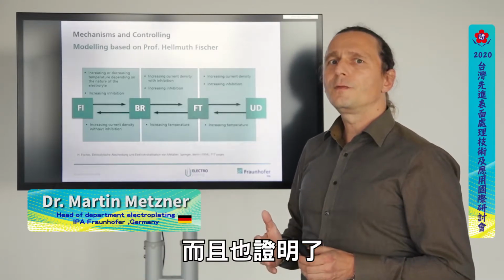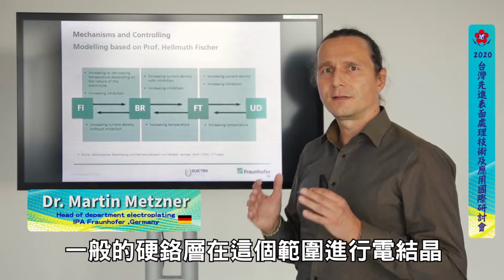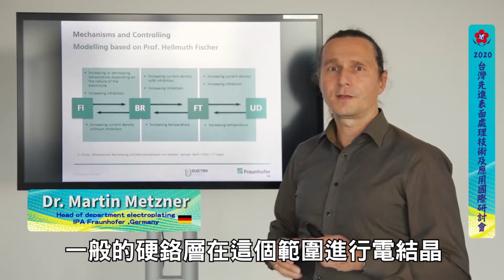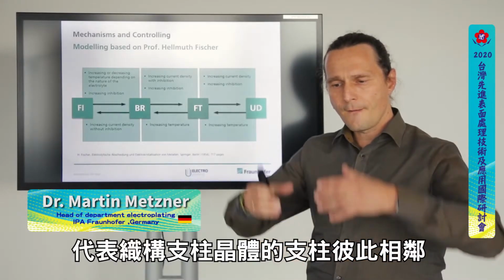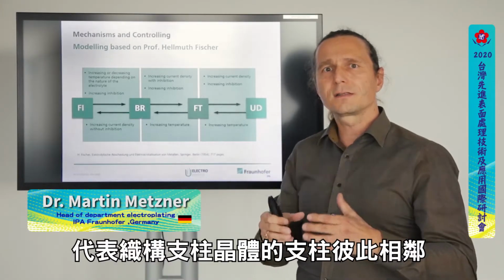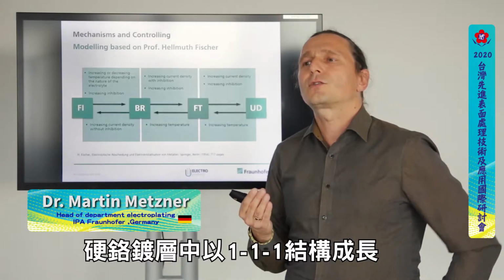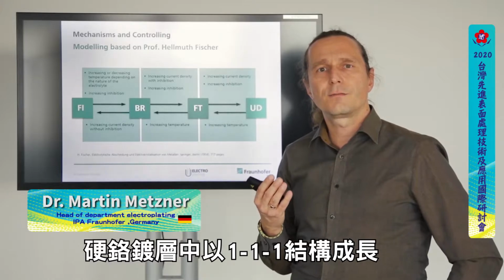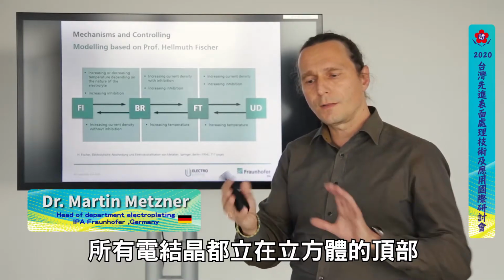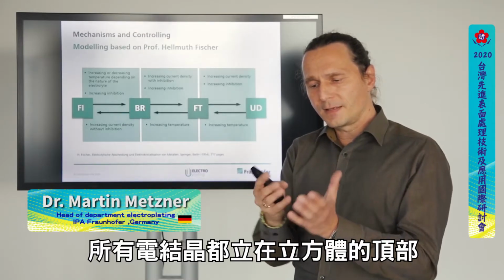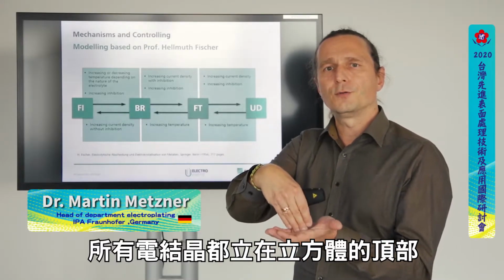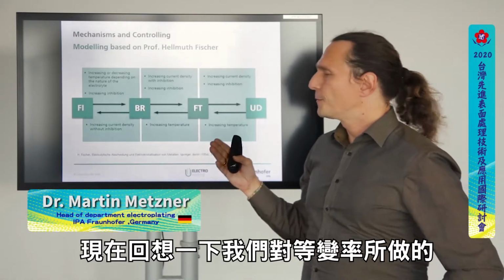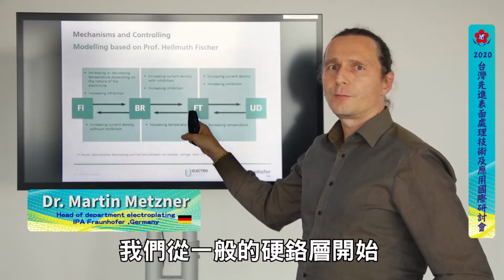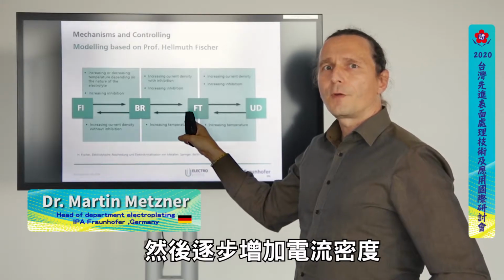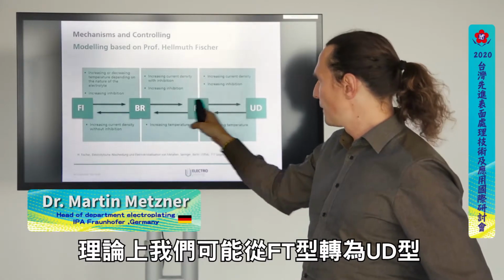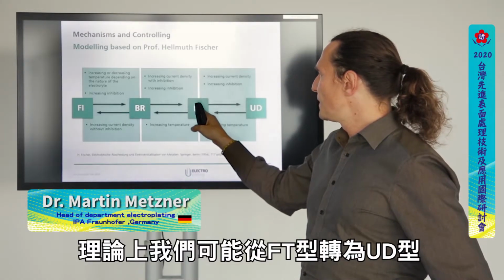And what's also proven is that normal hard chromium layers do their electrocrystallization in the field-oriented texture type. This means of textures, pillars of crystals stand next to each other. And in hard chromium plating, they grow in a 1-1-1 structure. So all the crystallites stand on the top of a cube. So when you think back now to what we do in our ramp, we start here with the normal hard chromium layers, and then we go step by step with the current density. This means it is theoretically possible that we change from here to this type.